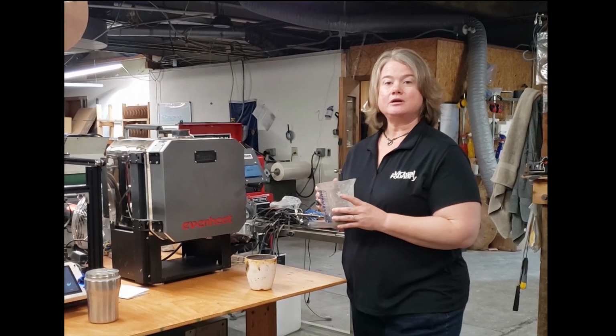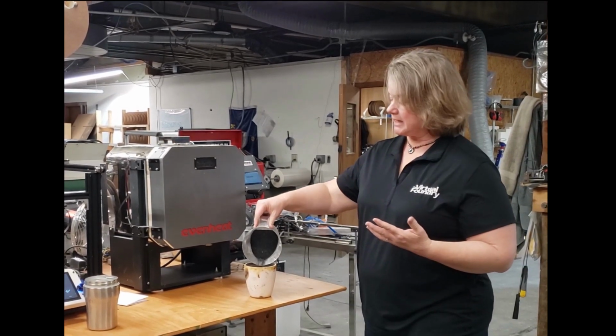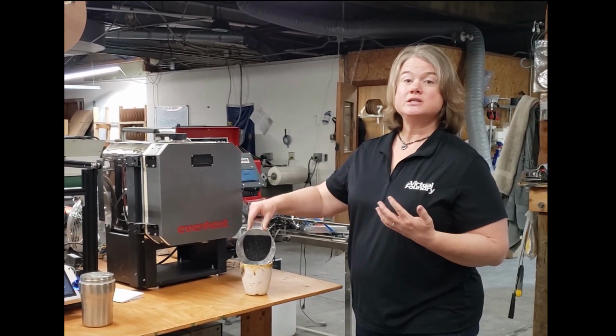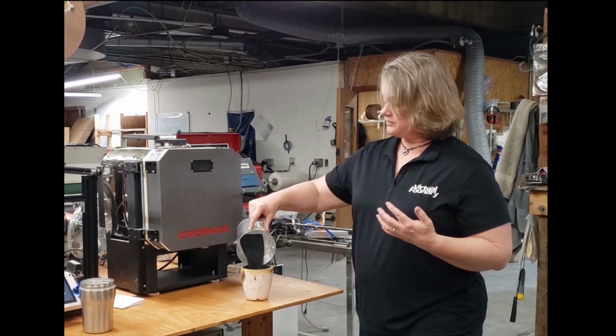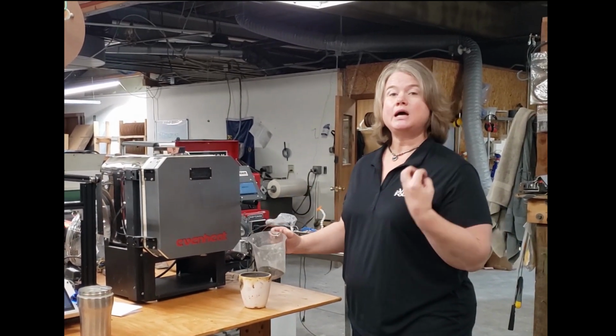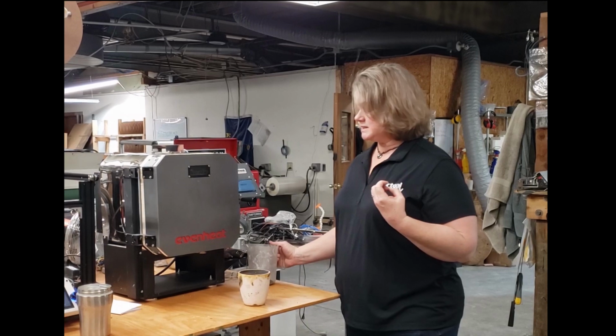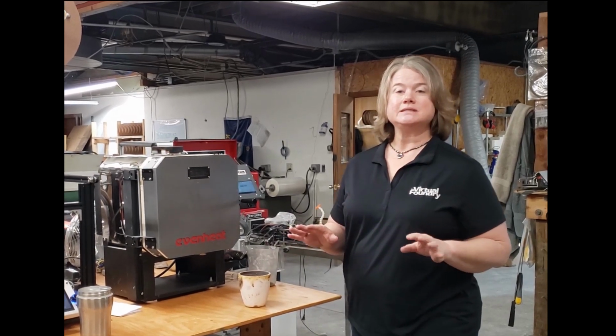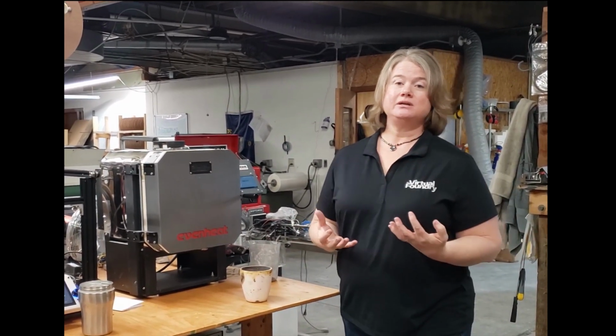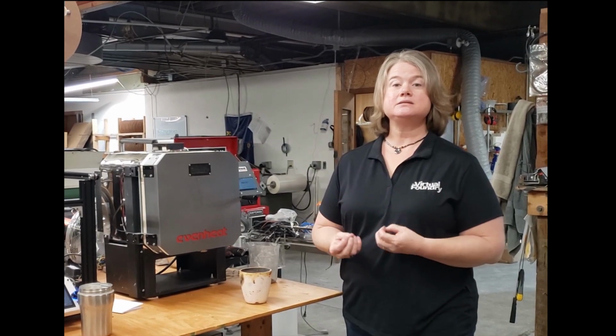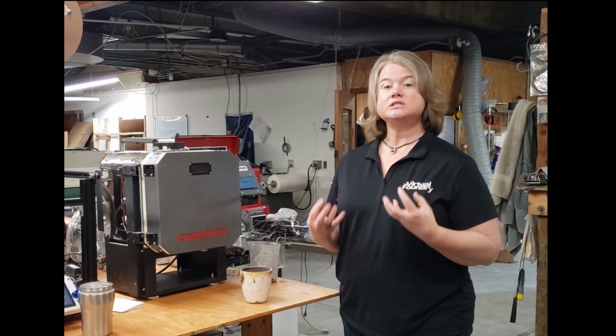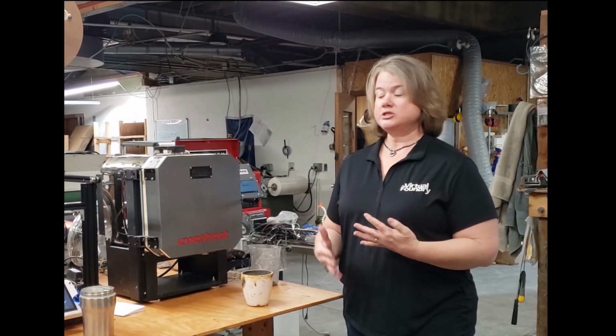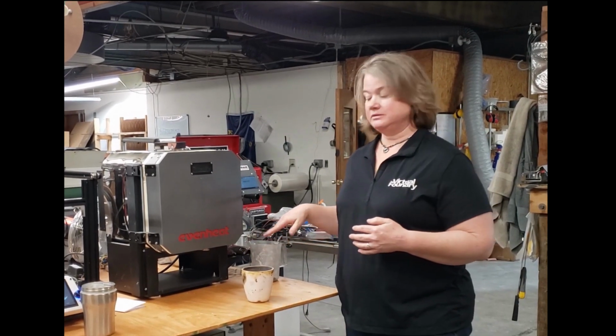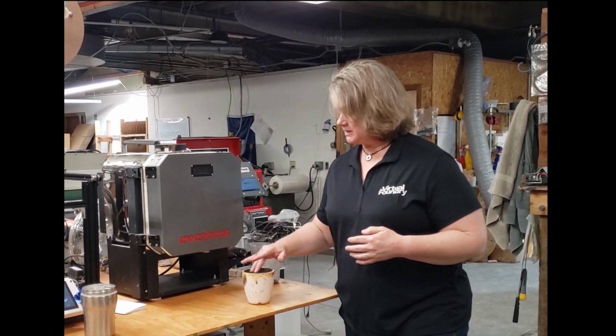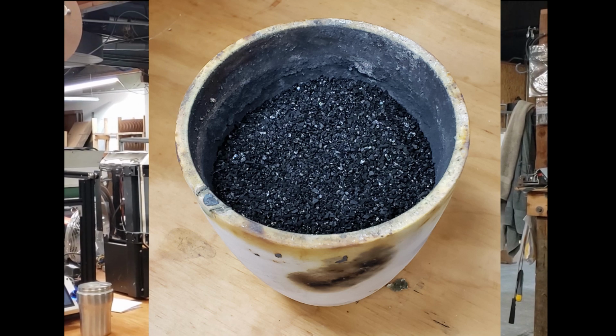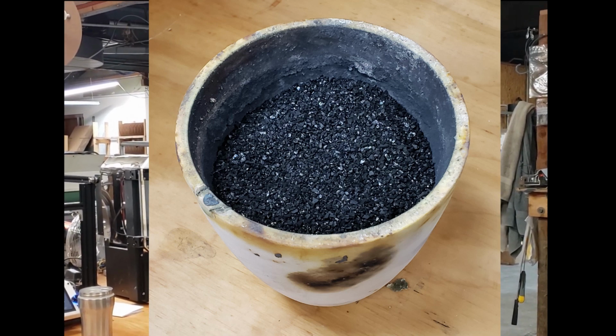So I've got my sintering carbon here. I'm going to add plenty of that on top. Now you really can't use too much sintering carbon. The job of this material is to consume oxygen during the sintering cycle so that it never gets to the print. Oxygen is damaging to the metal sintering process, so we want to make sure that we're shielding our print from oxygen using sintering carbon. So now I've got my sintering carbon on top in a nice thick layer. Back into the kiln it goes.